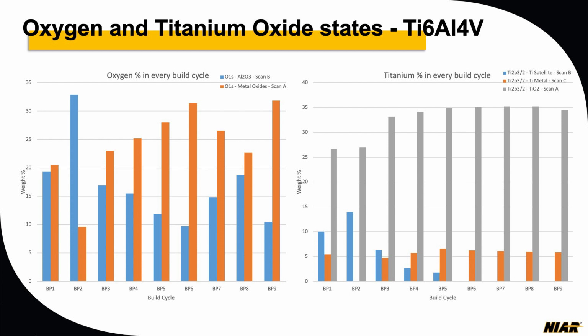So in here you have metal oxide that is constantly increasing over time. If you have to reuse the metal powder, there has to be some kind of parameter or cleaning process or some other heating process if you want to reuse it. But there are already some published papers in the industry on reusable powders and what it affects, because if you have more oxidation, your laser power also is going to be high.